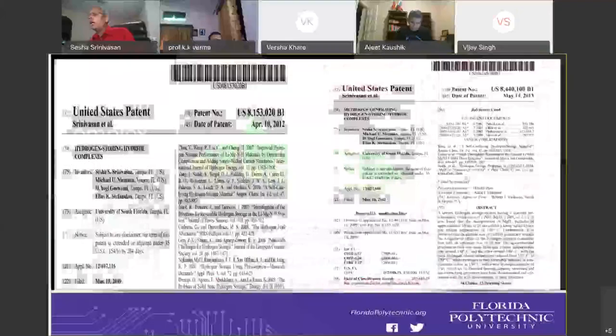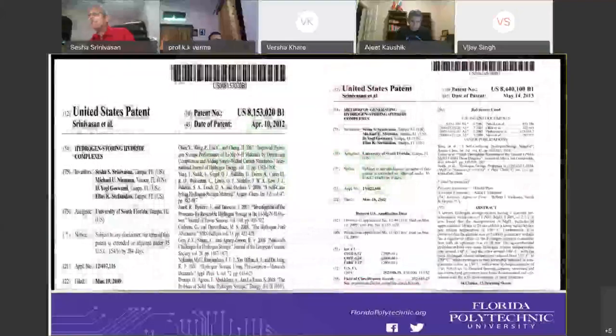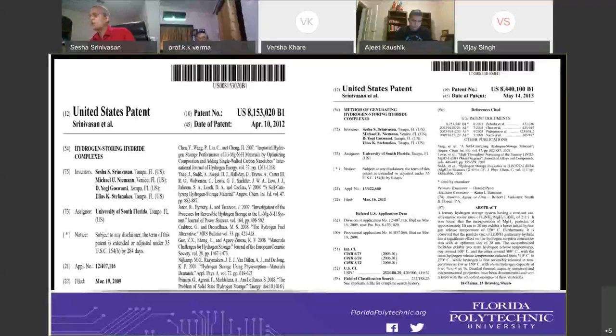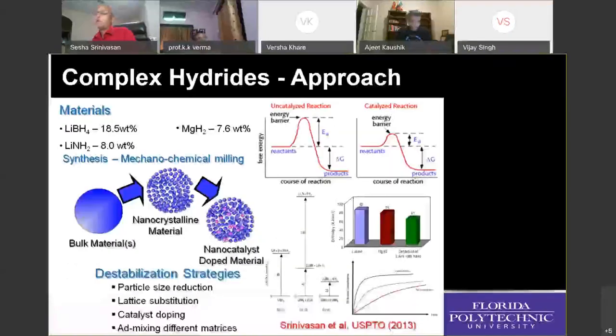Then after my life at the University of South Florida, we patented two patents on these methods of storing hydrogen and also nanotechnology enabled hydrogen storage. This was highly adopted by many of the companies. In these patents, we tried to make the bulk material nanocrystalline using planetary ball milling and then nanocatalyst doped. That means we will use a catalyst for doping so that you can improve the thermodynamics and also the kinetics. The thermodynamics I can decrease from 82 kilojoules per mole to 61 kilojoules per mole, and the kinetics is improved by 10 times. So I used different materials, like this composite system, to make this.